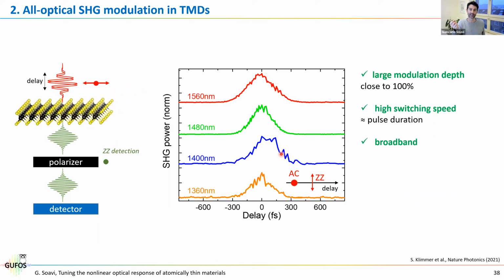The problem is that, as I told you before, the OPO that we have starts from 1360. So all the wavelengths that we have available are in the infrared, all below gap. We could try to take the second harmonic of one of those and then start from 600. But then the second harmonic is at 300 nanometers, and the efficiency of any silicon detector when you go to 300 nanometers is very low.